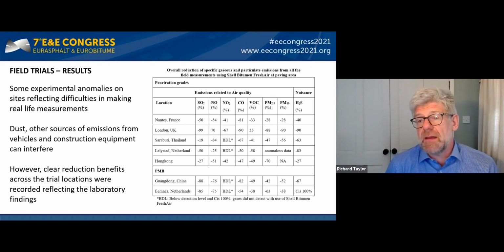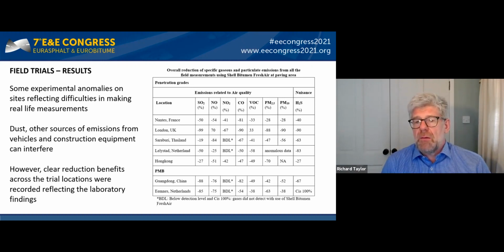So if we take a look at the NO and NO2, yeah, mainly in that sort of 50 to 75% reduction there. We had some very high reductions in SO2 in some sites. You'll also see there are one or two areas where we had some co-exposure, or we believe we had co-exposure. We had some below detectable limits. We had some anomalous data I referred to there from the field trial, which was close to an airport.